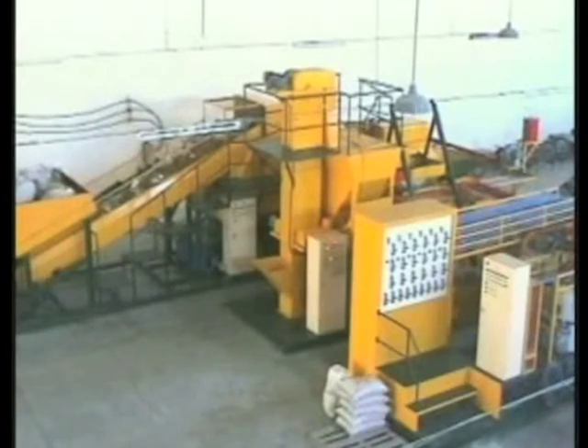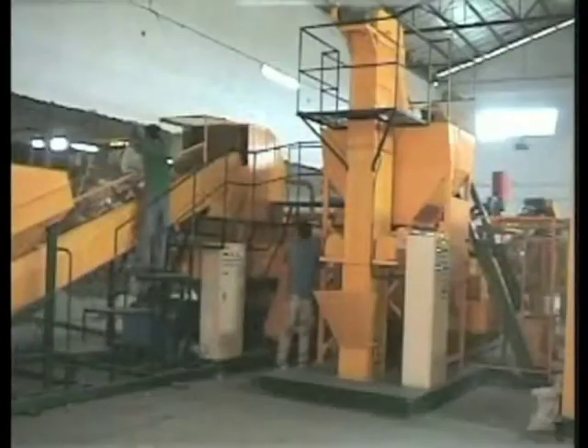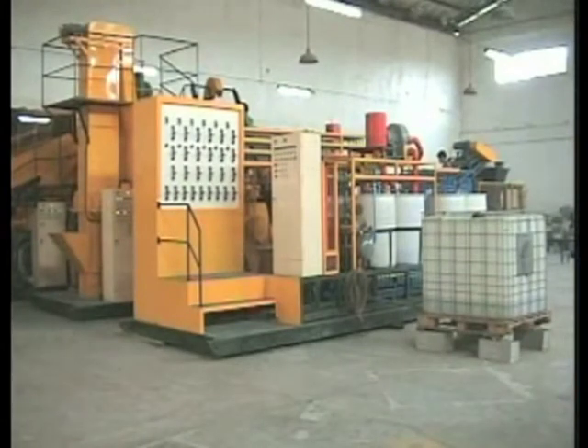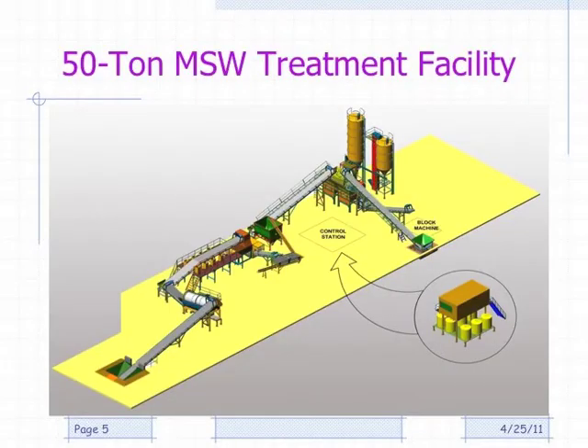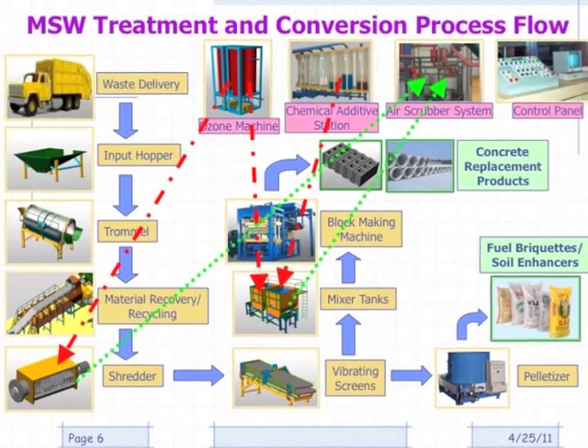The Toxicity Characteristic Leaching Procedure (TCLP) is a protocol used by the USA which tests for leaching toxins from concrete submerged in water. These tests proved in all cases that the heavy metals originally present in the waste feeds were neutralised and stabilised, and that the leaching was under the required levels of acceptability. In the more stringent Synthetic Precipitation Leaching Procedure (SPLP), which replicates the effect of acid rain on concrete, the results prove that in most cases the leaching was contained within the levels required for drinking water quality.